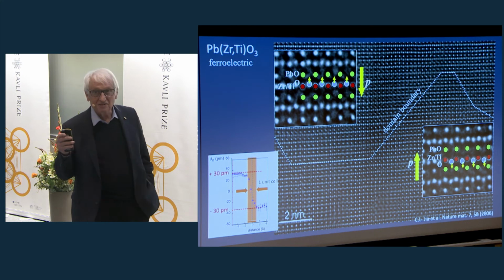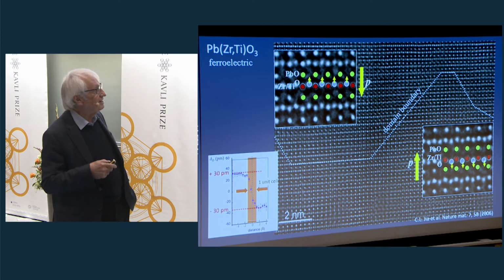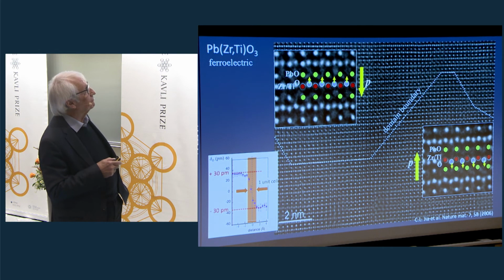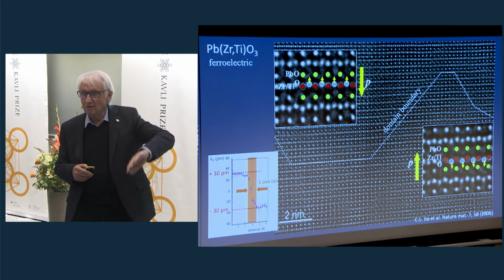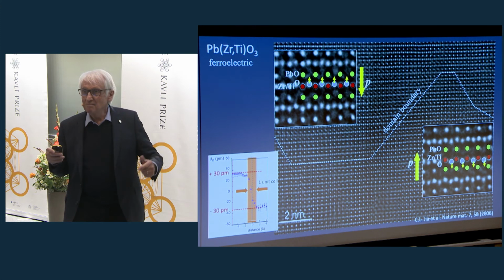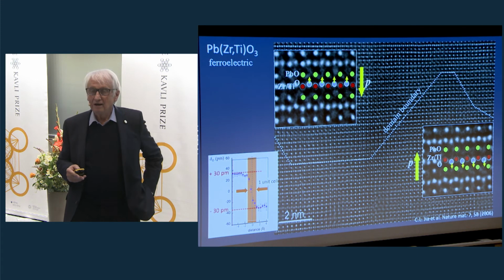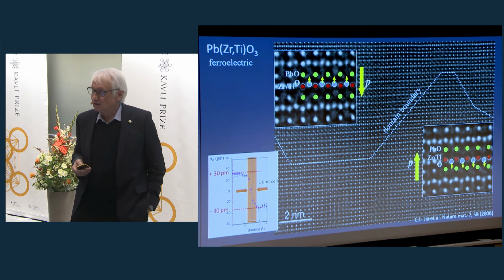So what is the nice thing here is that we see directly the shift of the oxygen atoms by 30 picometers up or down. And this can be used to do an electrical function.